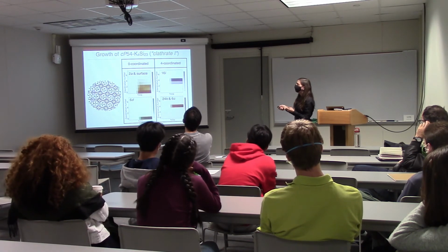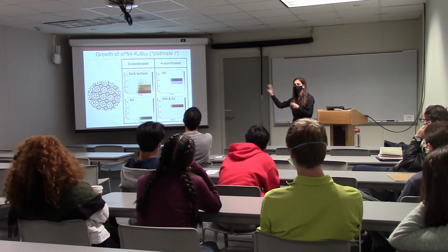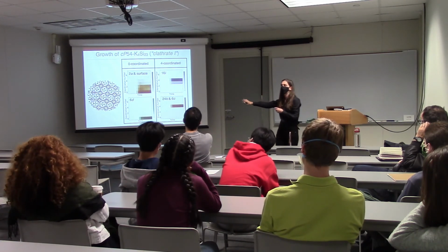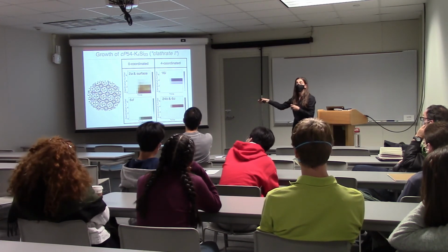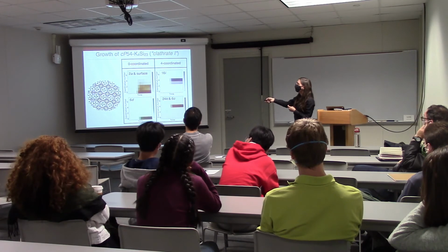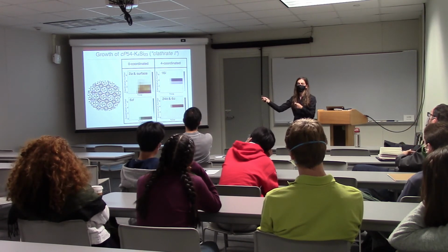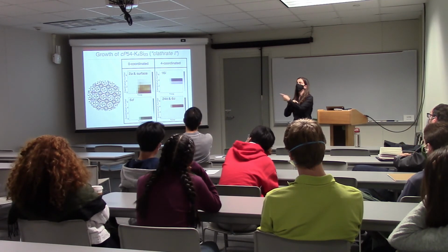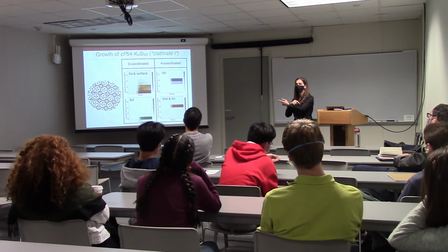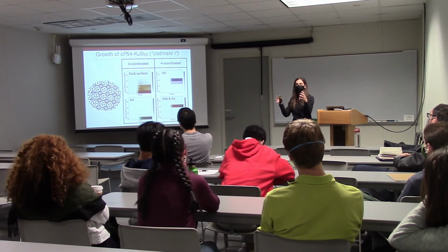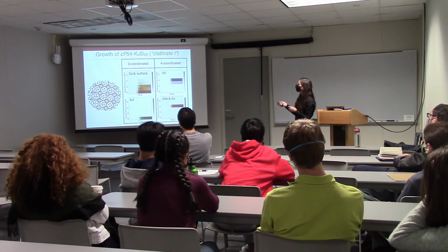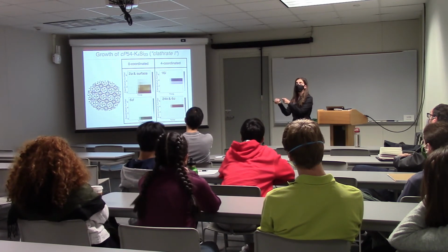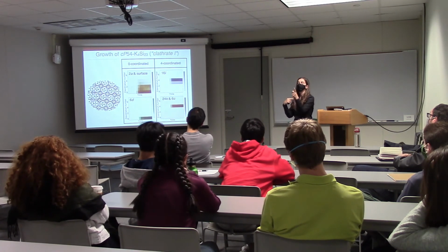The zero coordinated particles are almost never able, and I don't have plots for this unfortunately, but this is a really recent analysis that my student has done, they don't exchange almost ever with the framework. So you almost never have an exchange of zero coordinated particles with the four coordinated ones as soon as your crystal is condensed, whereas the particles in the framework are diffusing. So they can go back and forth between different micropositions.